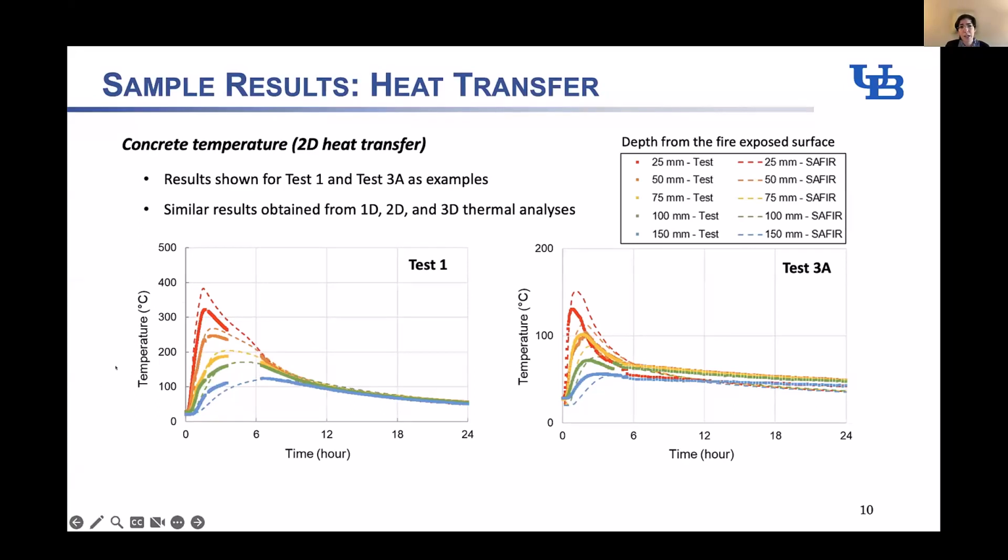specimens. So we actually had a concrete truck on site, and during pumping, these thermocouples were attached. They were pumping concrete, and we are aware that maybe we couldn't really control it. Some of the thermocouples might have moved a little bit, maybe a few millimeters, considering the pressure of those concrete pumps. So bottom line, looking at this, all the differences are less than, I would say, 80 degrees Celsius. That was the maximum error we had in all of our simulations.